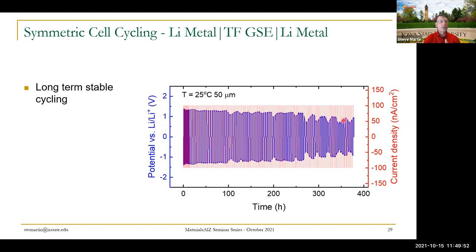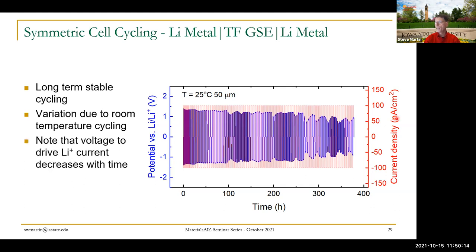We didn't think about it, but the temperature in our laboratory is cycling daily. We've since figured that out and thermally isolated the cells better, but that's what that is. The decrease is the cell getting better with time. The oscillation is showing up from the temperature isolation. But if you look over here, these are nanoamps, because remember, lithium metaphosphate is a poor ion conductor.